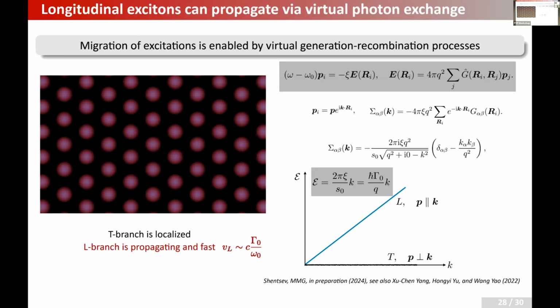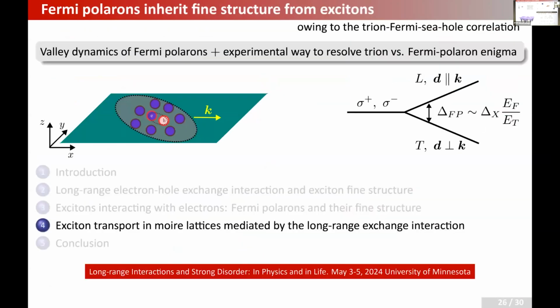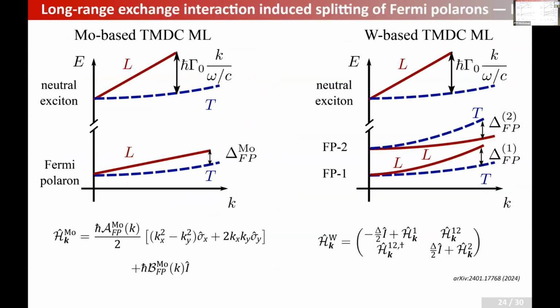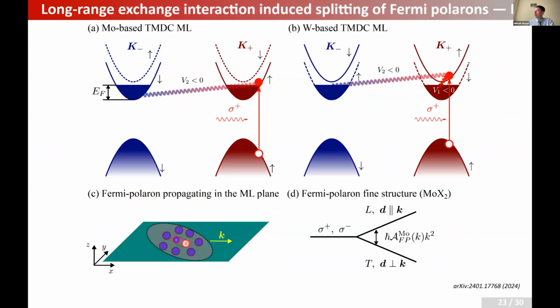Yes. So for your Fermi polaron picture, do you have some kind of numerical estimate of what the potential mass of this Fermi polaron is? Okay, it's a good question. I'm sorry for not having the slide at hand. For reasonable parameters, the effective mass of this Fermi polaron would be something between the A exciton effective mass and, let us say, the B exciton effective mass. So for reasonable parameters of transition metal dichalcogenides, it should be something between, say, the free electron mass and probably 1.5 times the free electron mass. It is much heavier than trions in some sense. In a way, yes, but not much. I mean, there is no parameter, at least for the range of densities we consider.